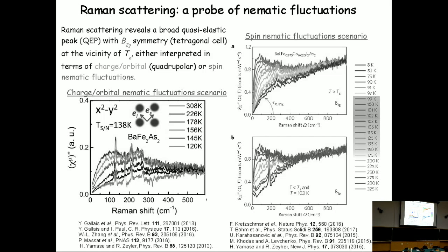And there are several groups making arguments for charge fluctuations as the generator of the Raman signal, and some groups making the case for spin nematic fluctuations as the generator of the Raman signal. This signal here, as you see, has a maximum at a temperature of around 140 Kelvin, which is very close to the magnetic ordering temperature in this system, and also, of course, to the structural transition temperature. Then it goes up to this temperature, then goes down below. It has the right symmetry. It is B2g symmetry for the tetragonal unit cell. It has the right symmetry in both mechanisms to be associated with the nematic fluctuations.